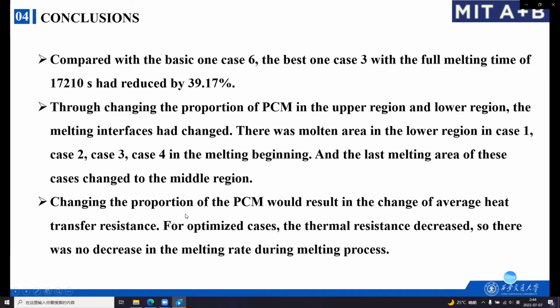And changing the proportion of the PCM would result in the change of average heat transfer resistance. For optimized cases, the thermal resistance decreased, so there was no decrease in the melting rate during melting process.